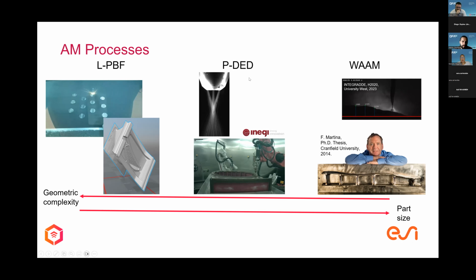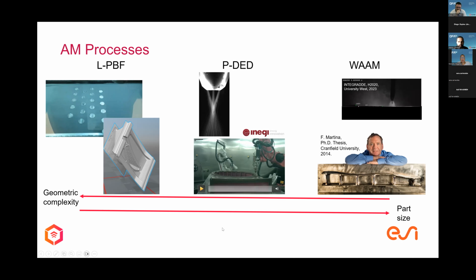Then we have powder-based direct energy deposition, where you usually have a coaxial nozzle. The laser comes in the center, heats a focus point where the powder particles meet together, and this is where the substrate will be placed. And here we have an animation of a part being repaired by Inegi.